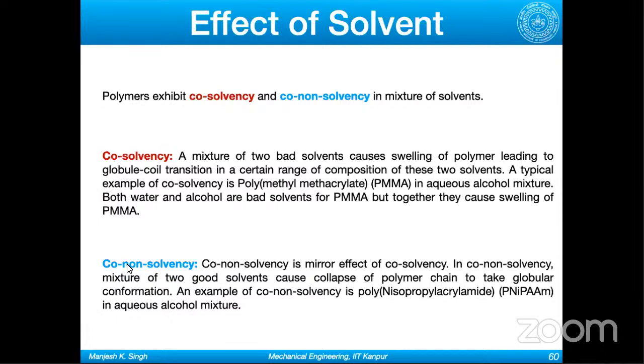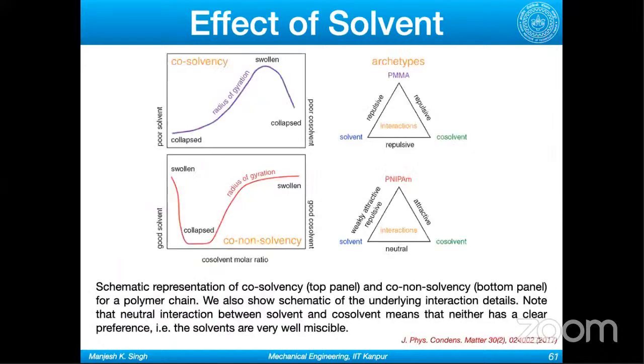Then there's co-non-solvency behavior as well for polymers, where two solvents are individually good solvents for the polymer, but when you mix them together at a certain mixing ratio, they behave as if they're a bad solvent for the polymer, and the polymer will collapse and will not form a brush-like structure. So we can exploit it to design smart lubricants. So what do I mean when I say collapsed or swollen?